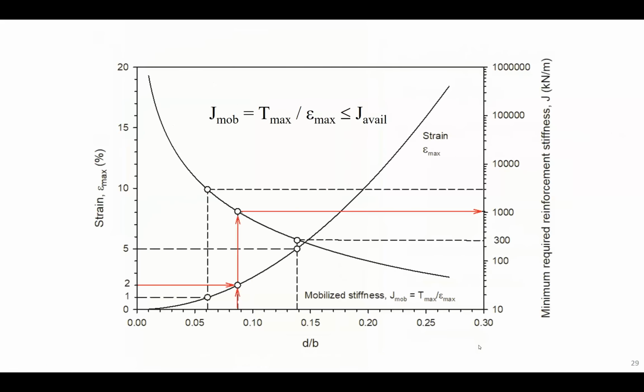So here is a chart that sort of summarizes some of the points that I've just made. When you use this method, you have to assume a ratio of reinforcement deflection at the void, normalized with the void width, and that gives you a strain curve that you see here. Knowing what this strain curve is, you can now find what the mobilized stiffness is, because you have the strain and you have the load, and this is the mobilized curve. And what you do is you make sure that that mobilized stiffness doesn't exceed what's available to you.